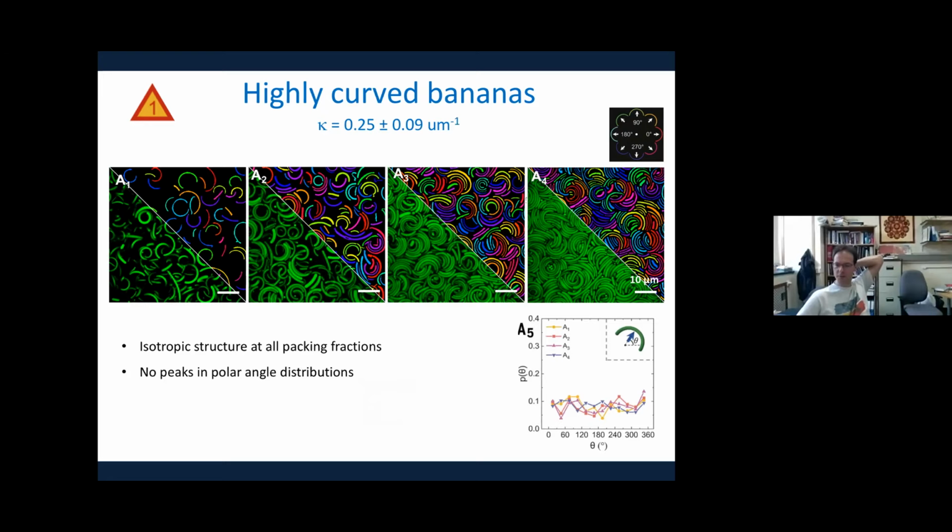I'm not very much an expert in active colloids. The issue with active colloids is sometimes they have this metal, half-metal-coated structure, if you want to make some of these Janus particles. I think metal is always difficult in optical tweezing, but let's say you don't have that. In principle, yes, you probably could. What is important is that the density, the packing fraction, of the coexisting phases has to be very different from each other. You need a large coexistence gap to be able to do this, because you rely on the optical contrast between the two phases. If you're close to a critical point, it doesn't really work very well. If you can achieve that with active colloids, then I don't see a reason why not, other than the details of the particles that you use.